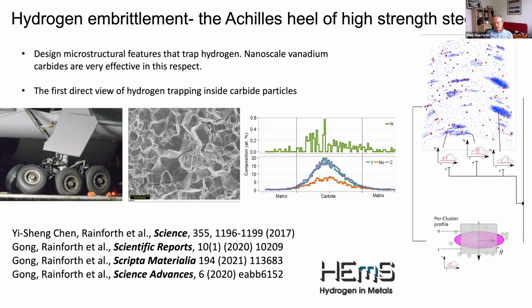Of course, and I'm not going to talk about this, although I'd love to do so, that pushes into the realm of hydrogen embrittlement. Typically, when we get above about a gigapascal strength or thereabouts, depending on the specific steel composition, then we're into the regime where hydrogen embrittlement becomes an issue. So we have an image there of a failure from hydrogen embrittlement, the typical sort of intergranular failure in the middle there in the SEM image, where you get cracking extensively.